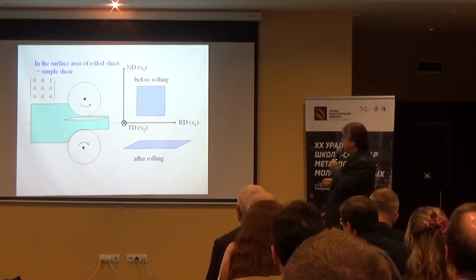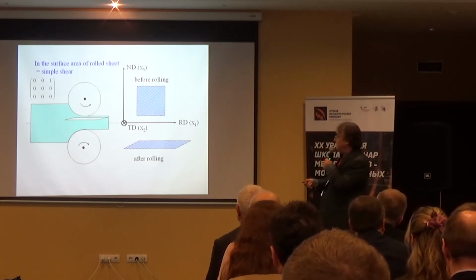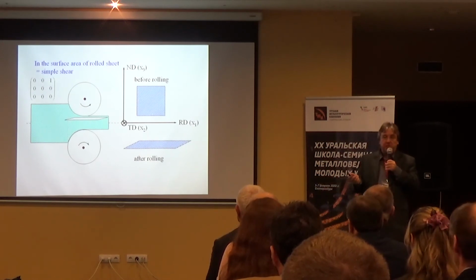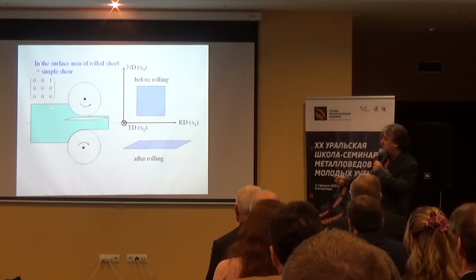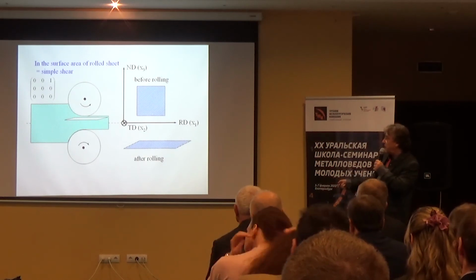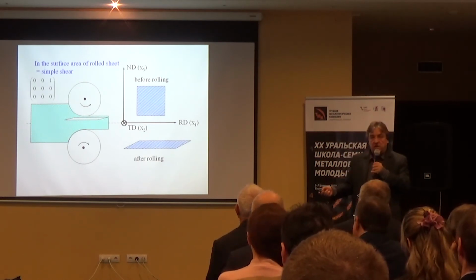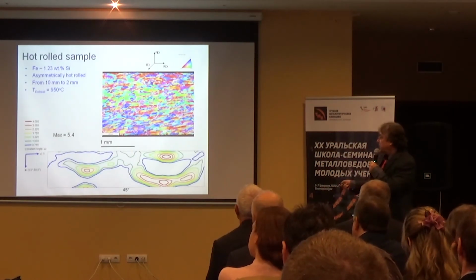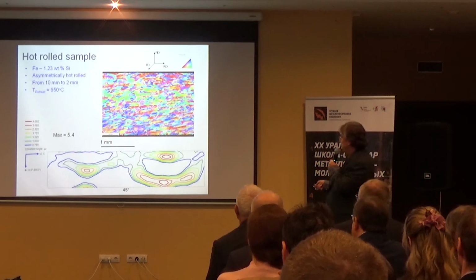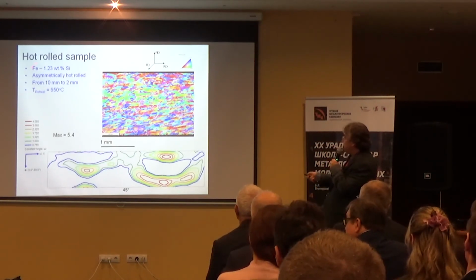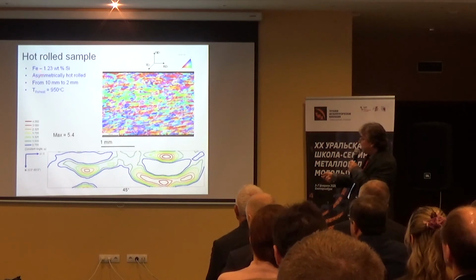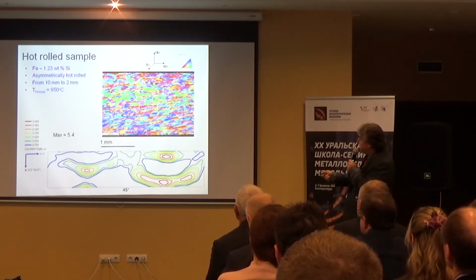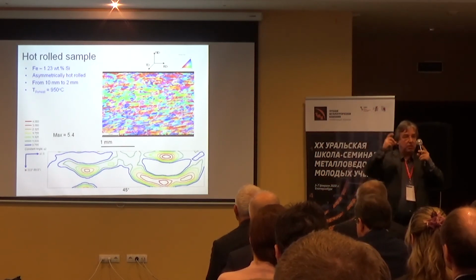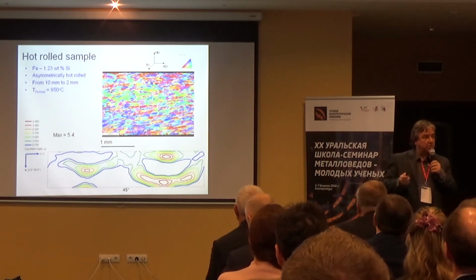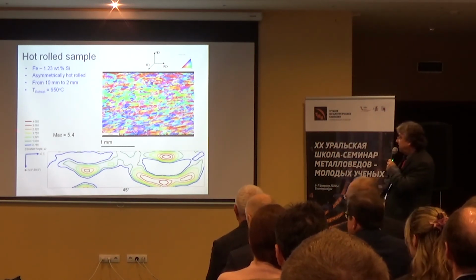Now, it is sometimes more complicated because in real life rolling, you do not only have plane strain compression. You may have a combination of plane strain compression and surface shear also. So then the strain tensor becomes more complicated. And here I have such an example in which we did a roll. This was hot rolling of an iron 1.23% silicon sample, it was asymmetric hot rolling. That means that the rolling diameter of the top and bottom roll was different. And then this is the deformation texture.